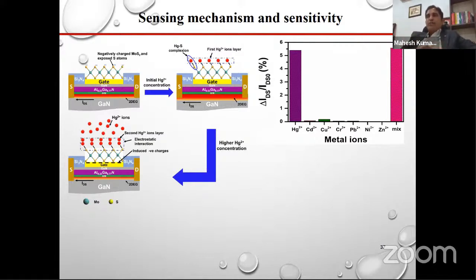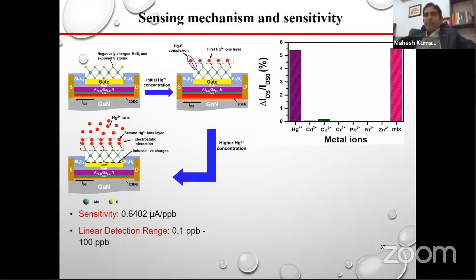Another important parameter, as I said, is the selectivity. How much selectivity is there? We have tested zinc, nickel, and other heavy metals. Also, we have mixed all, and we found this one is highly selective. If you see, the sensitivity is also good, around 0.64 microampere per ppb.